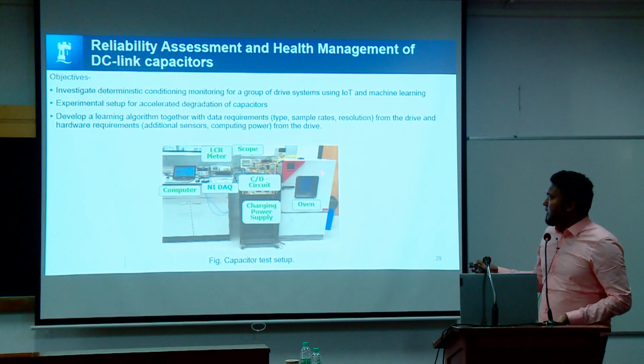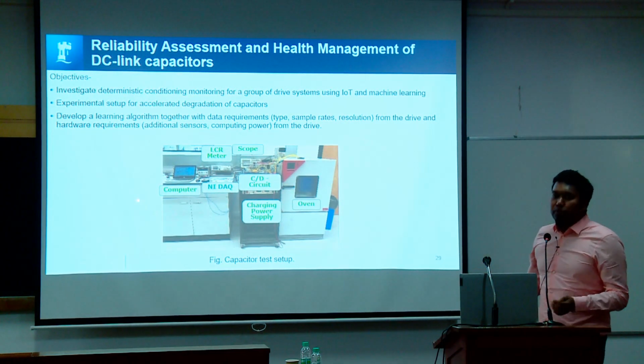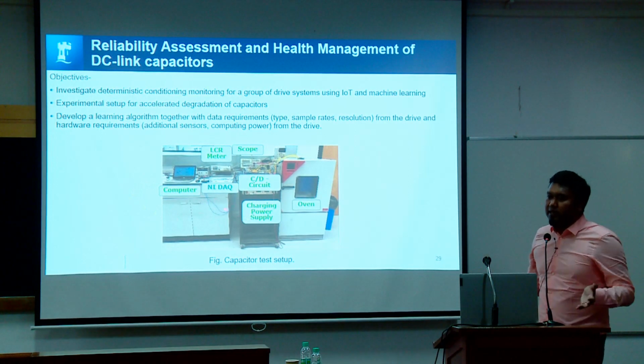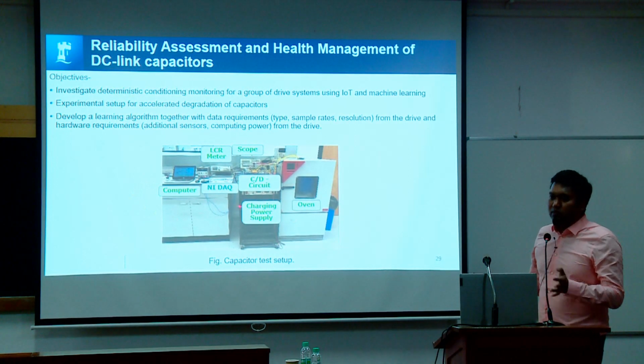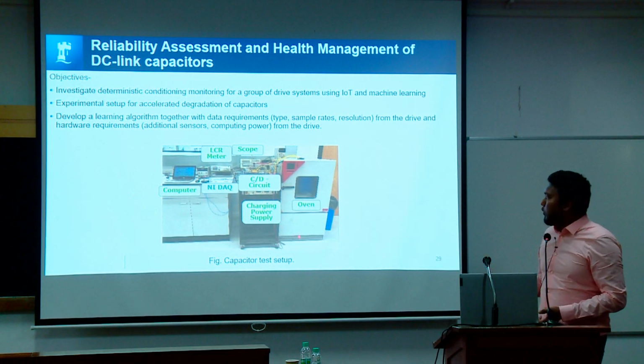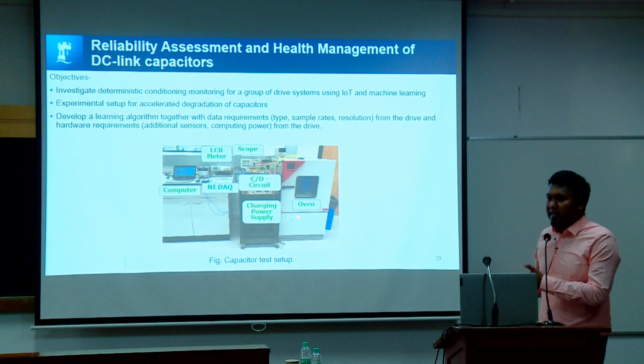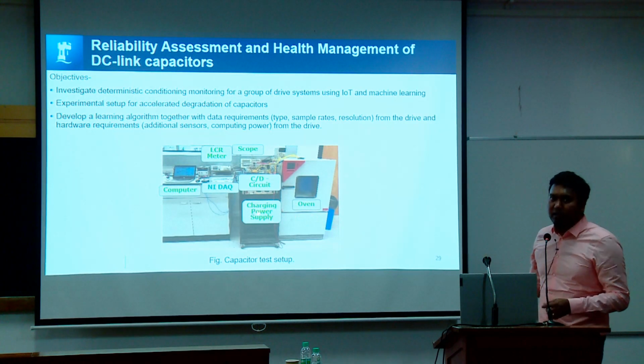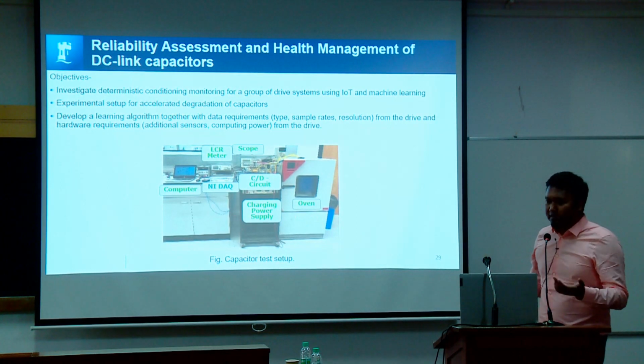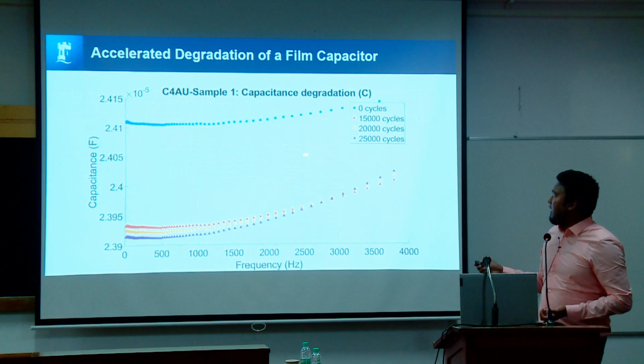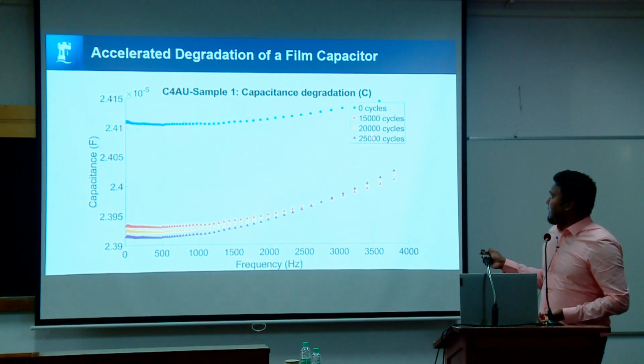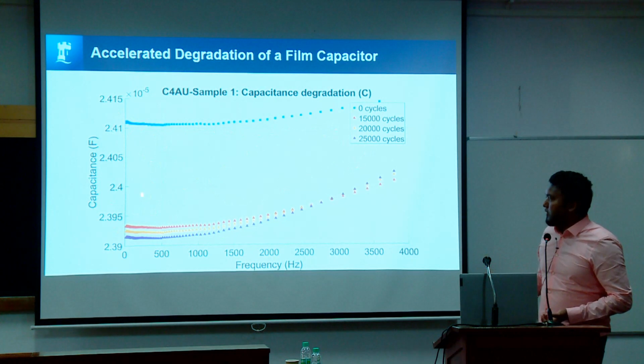We put the capacitor inside an oven, and with a circuit controlled by an NI DAQ, we charge and discharge it for thousands of cycles. After maybe 1,000 or 500 cycles, we stop the test and measure the capacitor with an LCR meter, again trying to find out which parameters are changing. As you can see, after 25,000 cycles the change is clear. The blue line is the capacitance at 0 cycles, but as the capacitor ages, the capacitance starts to drop.